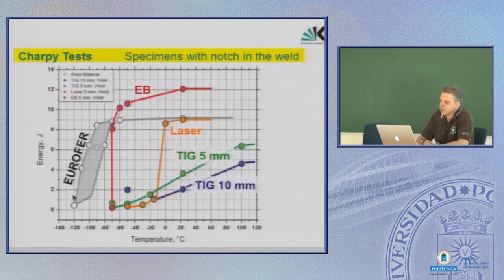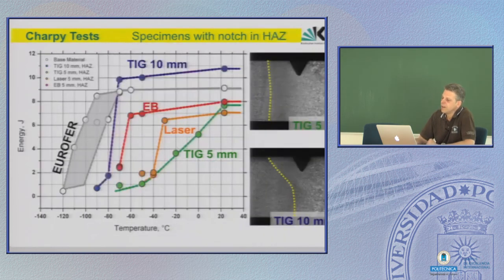This is the Eurofer regime for Charpy tests. The red one, that's electron beam welded, which looks not good, but it's still the best of all these variants. Laser weld is here, and this tungsten inert gas welded are there. So without any heat treatment, I wouldn't use these welds in Eurofer, but this we already knew, but here you see the effect in terms of Charpy testing.